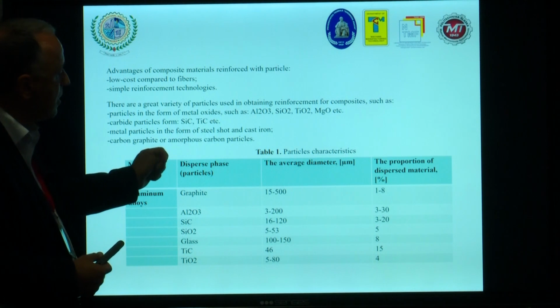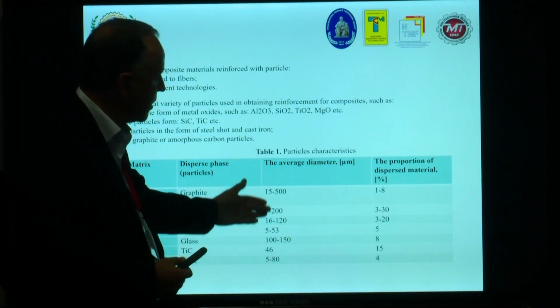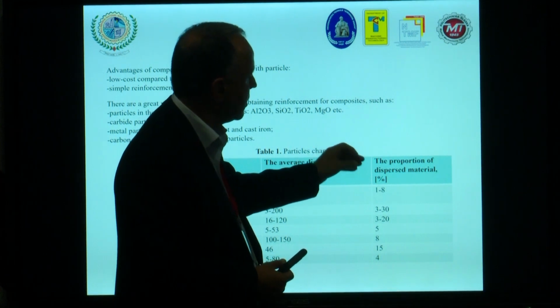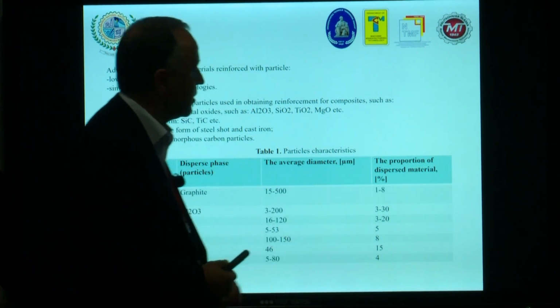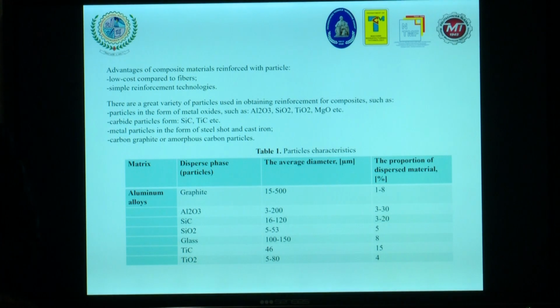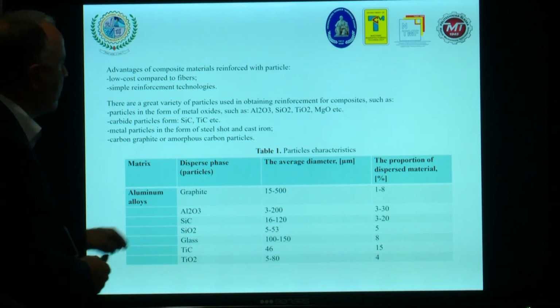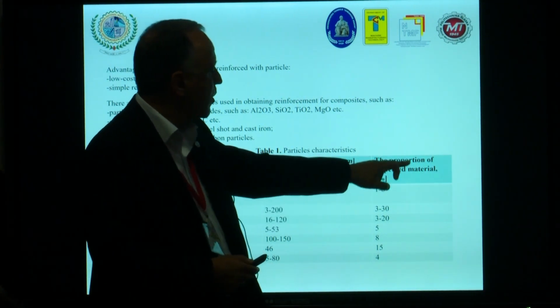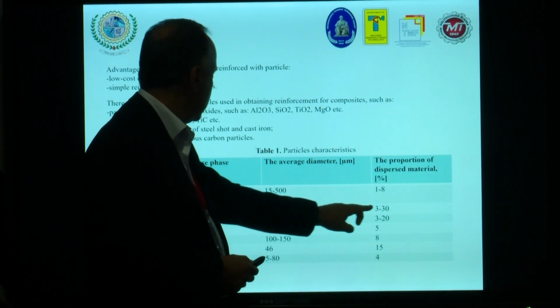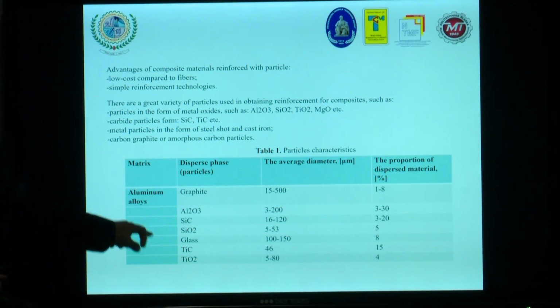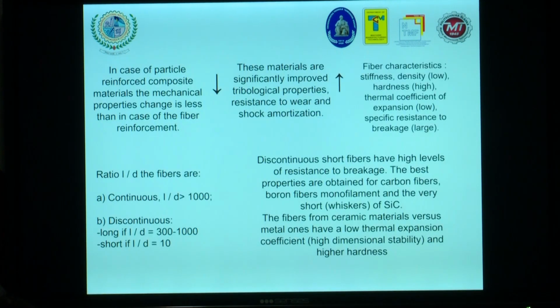I put over there, in case of aluminum alloys as matrix, which are the particles, the average diameters, and the proportion of the dispersed material. I mean, how many percent of the material is dispersed. So you can see the highest on graphite, but take into account the proportion of dispersed material, around aluminum oxide. One of the most used particles for reinforcement.